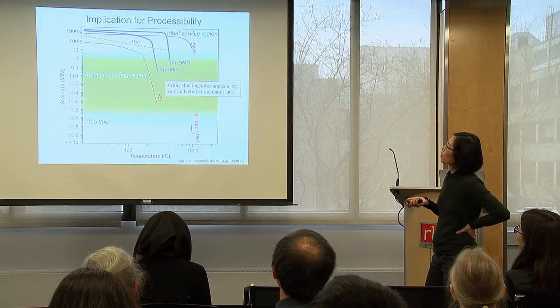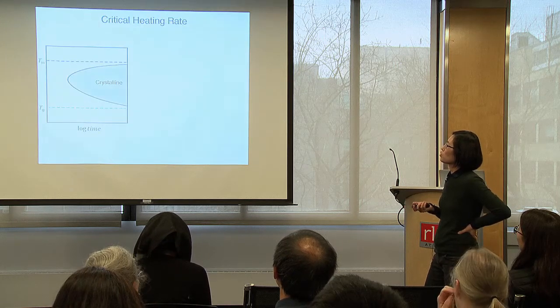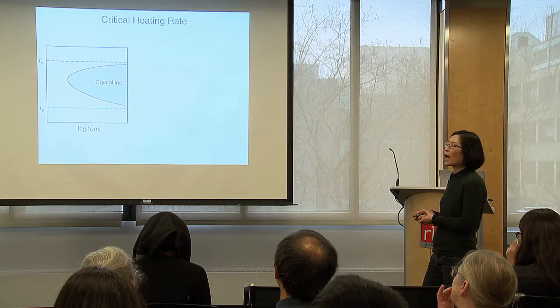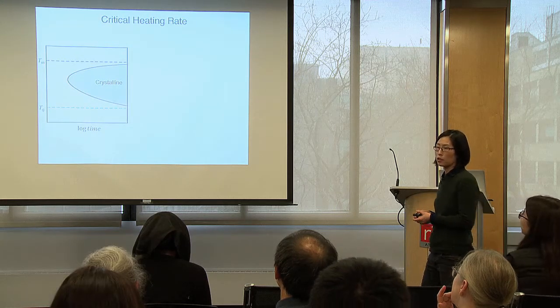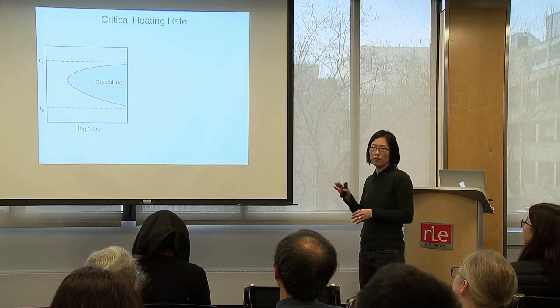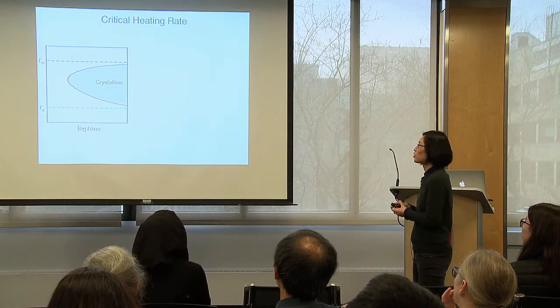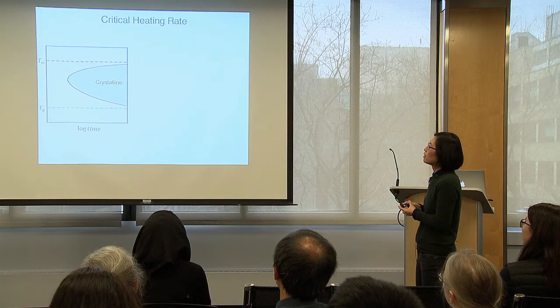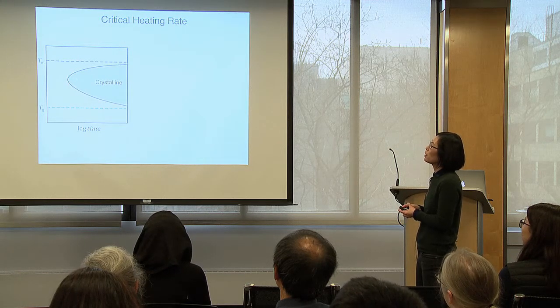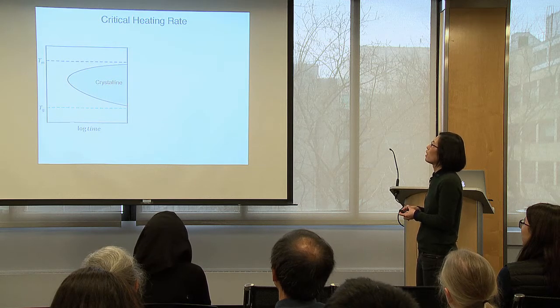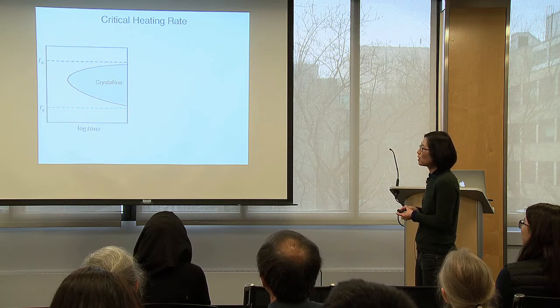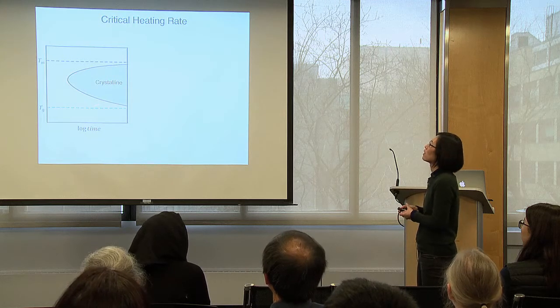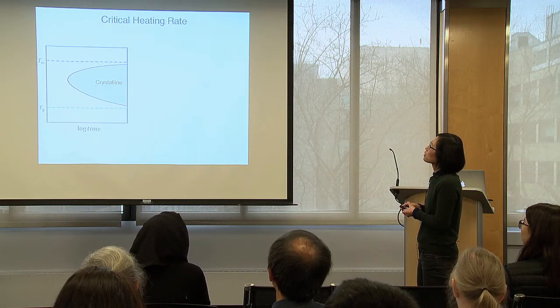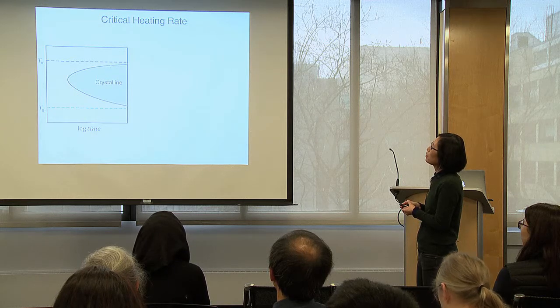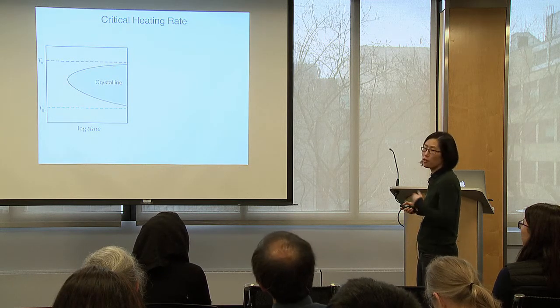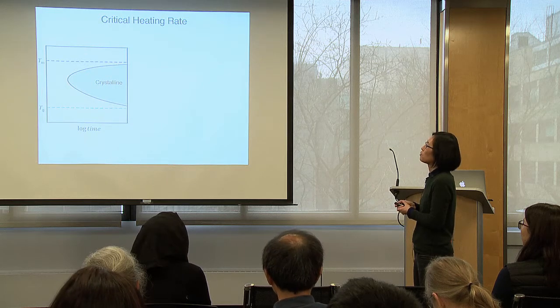And there's now what's called critical heating rates and cooling rates that are coming into play. So this is a time temperature transformation diagram. I will explain this for those of you who don't know. I had never seen this before I started studying nucleation. This is liquid here, okay? When you cool the liquid, it's going to crystallize, right? But if you cool the liquid super fast, it's going to become glass. Frozen liquid is glass. It takes some time to crystallize, and at high enough temperature, you don't have much thermodynamic driving force to crystallize because you have a lot of jumping motions.